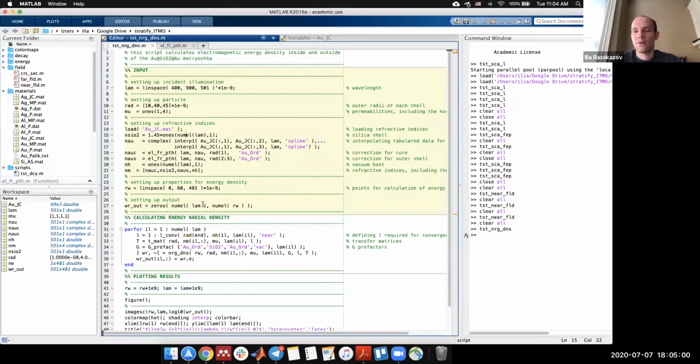But for a graphene layer, I would be a little bit careful because this is a two-dimensional material. I'm not really confident on how to describe the dielectric permittivity of a graphene layer. If that is a tensor value, not a scalar, then you need to derive new equations and solve a little bit different problem, where the generic shell of your multilayered sphere has a tensor permittivity. That is a little bit tricky. So to summarize, any material can be used as long as its permittivity is a scalar. If you're confident that the permittivity is a scalar, then you're fine.